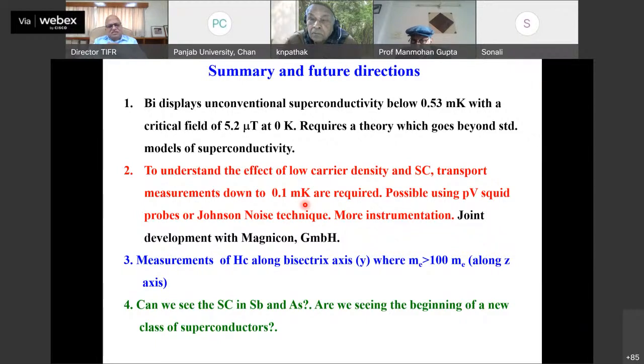So what is the way to measure resistance well below 10 millikelvin? The only way we can measure is, as I said, measure the noise. We are using the noise as a thermometer. So reverse this. You measure the noise with a noise thermometer, but you measure the resistance of the material using the same technique. And then from the noise, because you are not putting any current into the system, you can try to measure the resistance. And this has been done for the ytterbium rhodium 2 silicon, which I mentioned, by the group in England. We are trying to get a collaboration with the Magnicon group in Germany to do these measurements for the bismuth.